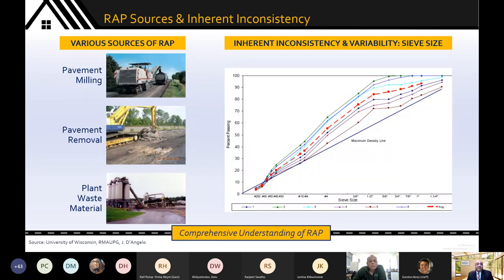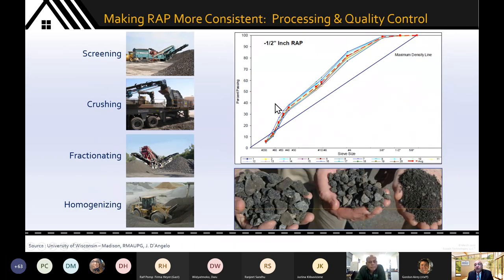So what are the sources of RAP? Again, all of you are familiar with this. Just a quick recital. Pavement milling, the 2-inch, 50 millimeter mill and fill type job, generates RAP. Removal of pavement completely, both the cap or the wear layer and the base course, generates a lot of RAP. Plant waste material. The consequence of generating RAP from all these materials is that you get an extremely variable gradation, sieve size, particle size gradation. Your goal is to take this material and reduce it to a much more uniform material that can be an input into your raw material operations.